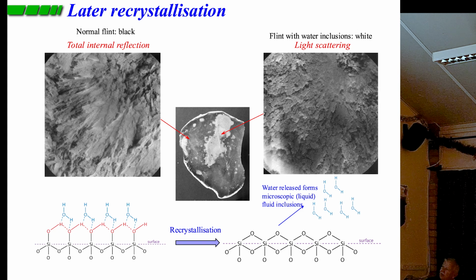And what can happen is if we recrystallize the flint a little bit, the diagram on the left there is a close look at this microfibrous chalcedony, and that's where most of the water is contained. But the reason flint looks black is because the microcrystalline structure completely internally reflects the light that goes into it. There's virtually no organic matter in the flint at all. It's just dispersal by light scattering.